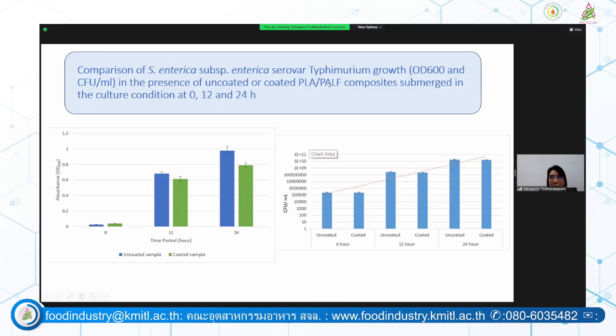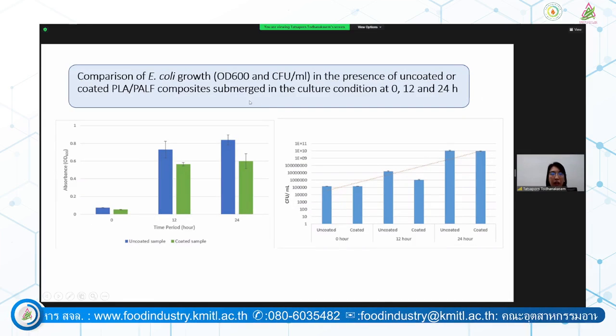Okay, and how about Salmonella typhimurium? It also shows the same thing. From 12 hours onward, you see a reduction in the number of bacteria based on the OD and the CFU. So somehow the compounds in the biomaterial that we make could diffuse to inhibit the growth of the bacteria in the solution. It also shows the same result and significantly affects the E. coli cells. From 12 hours onward, the bacterial growth is reduced based on the OD and CFU observation. After we tested this, we selected Gram-positive and Gram-negative foodborne pathogens to test. So the compound from the biomaterial that we make can inhibit both Gram-positive and Gram-negative foodborne pathogens that we tested.